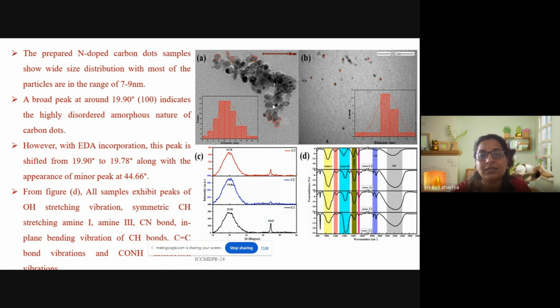And as we increase the amount of the EDA, the peak is slightly blue shifted, and the appearance of the new peak at 44.66 is also seen for the low amount of the EDA. The figure represents the FTIR spectra of all the N-doped carbon dot samples, where the abundance of the